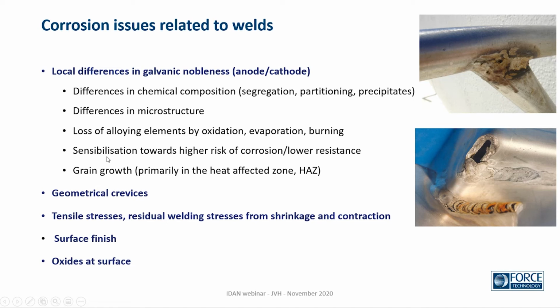We'll often see that the weld metal is higher in alloying to compensate for this loss. We also have a problem with sensitization, which means that the material gets sensitive to corrosion from change in microstructure during welding. Grain growth could also affect corrosion properties of the material and the problems that we would see in the heat affected zone. And also welds could have geometrical crevices from the design where we would have overlap, which would give crevices, or we could have weld defects causing crevices.